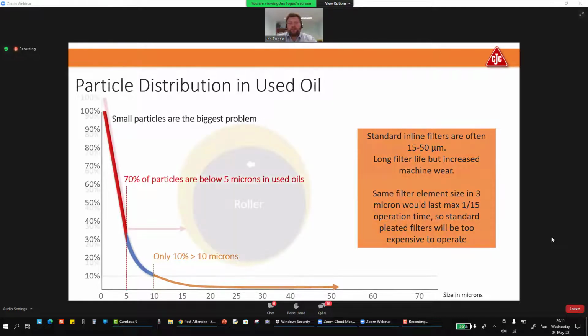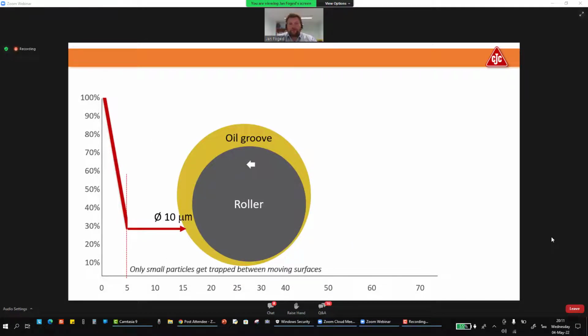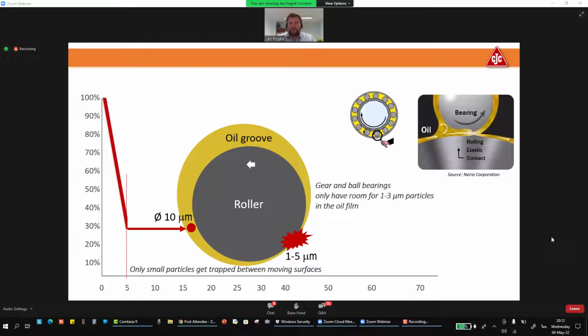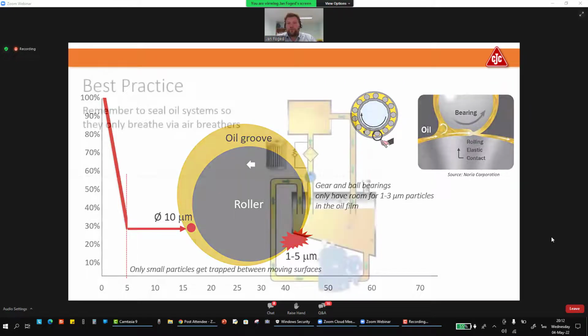Here's a picture of a rolling bearing system. As you can see, 10 micron is not a problem when it's in between the big tolerances, but eventually it comes in between the two metal surfaces and is crushed. It causes friction, wear and tear, and all of a sudden you have damage on your surface and on the roller bearing. So the small particles get trapped between the moving surfaces and cause more wear and tear. It's very important, therefore, to look at the tolerances, and the film, as we talked about, is between 1 to 3 micron, which most filters do not remove.